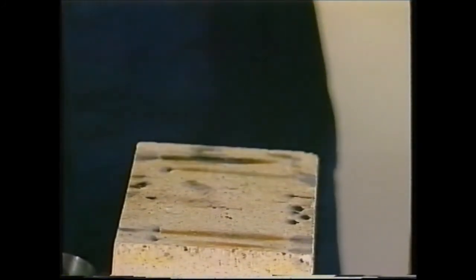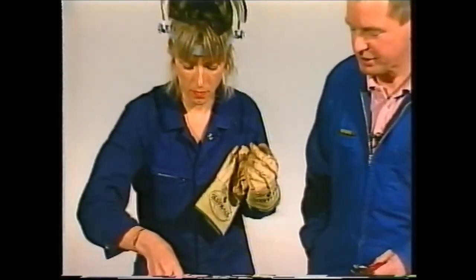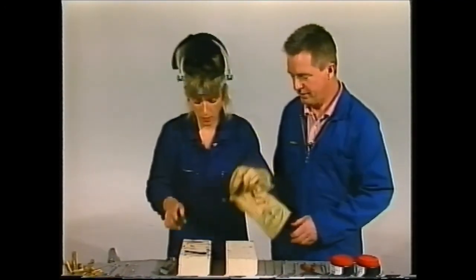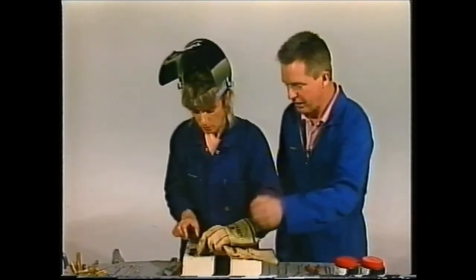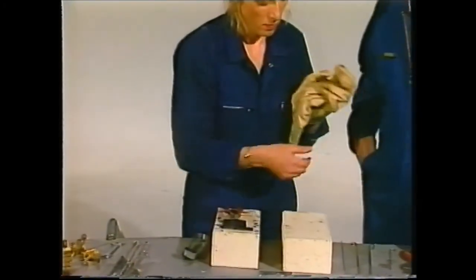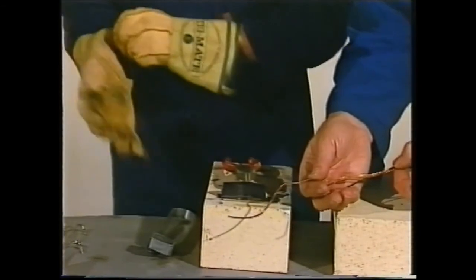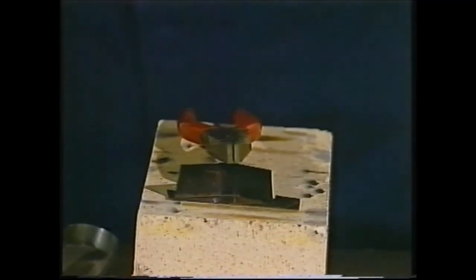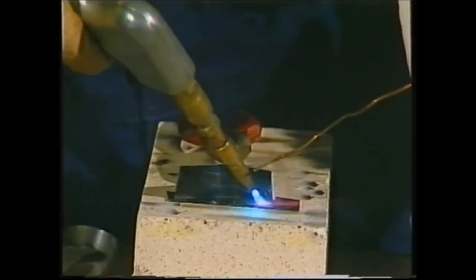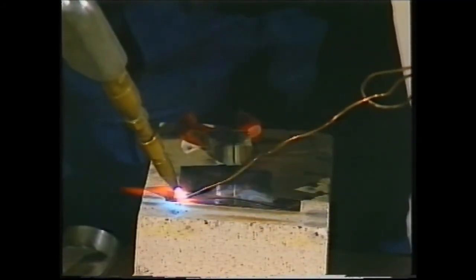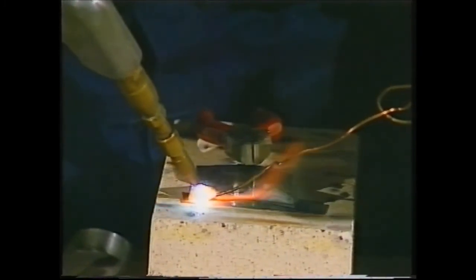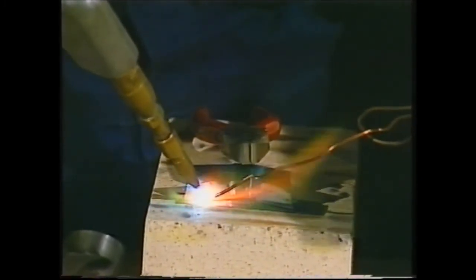Now the torch will also braze using the most unusual pieces of gear. Now here it is brazing a piece of spring steel packing strap. This is just old spring steel packing strap. You can notice there it has all the rust and rubbish on it. And what we're going to use for that is just a piece of standard copper wire. And we're going to braze with that. Now, if you tried this with a conventional oxy torch, you would very likely oxidise the copper wire away, and very probably shatter the spring steel. It's the torch's ability to pick up what's around and use it that makes it so amazing. And you'll see it'll run that copper wire around there rather like you would silver solder.